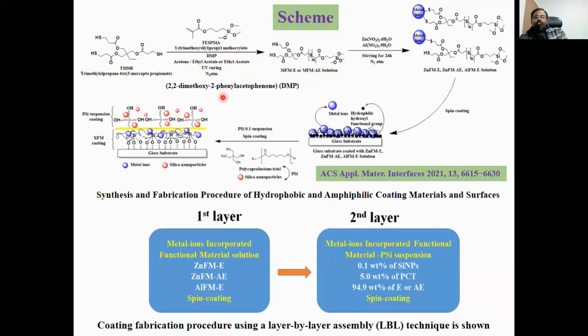using some photo initiator, and in this case we use zinc and aluminium. We also tried several other metal precursors, but we optimized only zinc, and aluminium is much better in this synthesis case. So we developed some metal ion loaded precursors, and then we coated this solution on a glass substrate. This coated substrate shows very good hydrophobic properties,